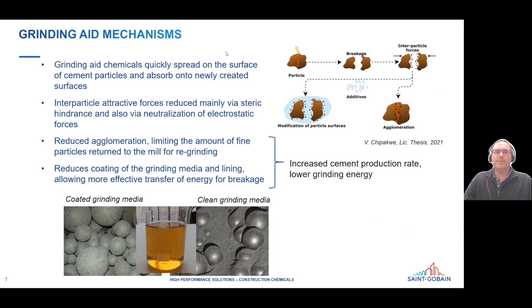So we talked about how that reduces agglomeration, which improves the efficiency of the grinding process. That agglomeration can actually happen right onto the grinding media as well. And so you can see that you get a coating on them if you don't have a grinding aid, and that actually cushions the blow. It makes it less efficient. So you get a more efficient energy transfer as well for breakage with the grinding aids.